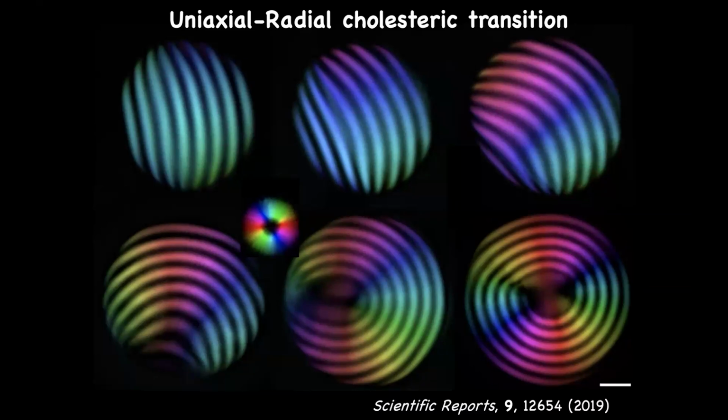So this is a very nice technique where each color corresponds to a map of the nematic field. Each color gives an orientation over 2 pi of where the nematic field is. And you see in the beginning we have uniaxial particles, then you start to see bending. This bending costs energy. Why does the system put energy in bending? Because if you keep going, eventually, yes, you have introduced bending, but you have given up the gamma omega part of the anisotropic surface tension. So it's what you have seen before.